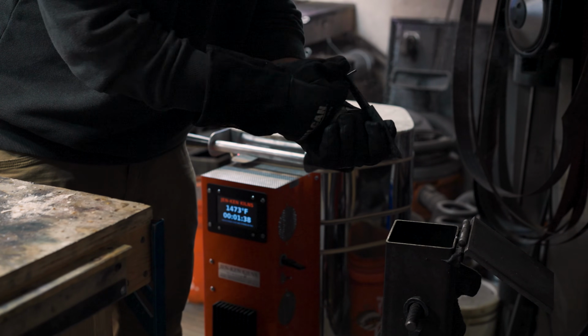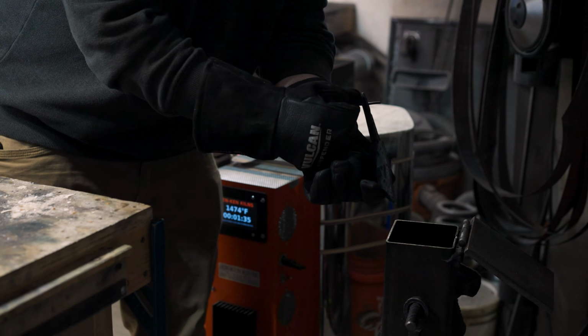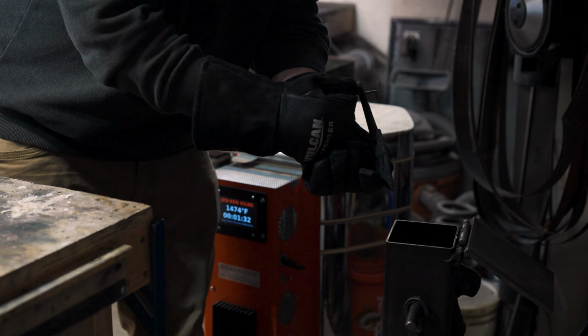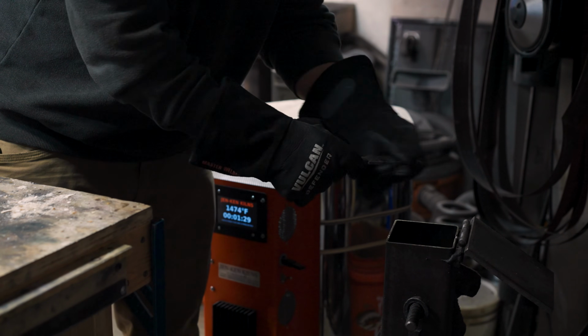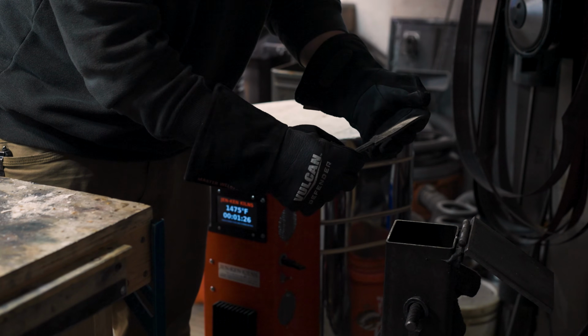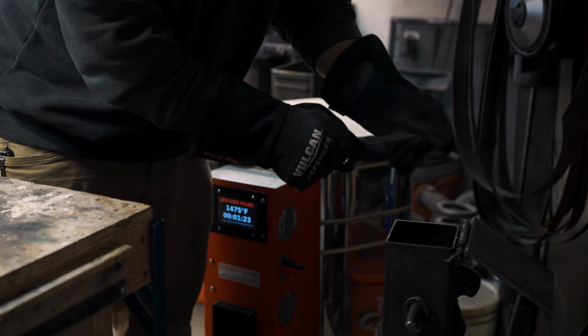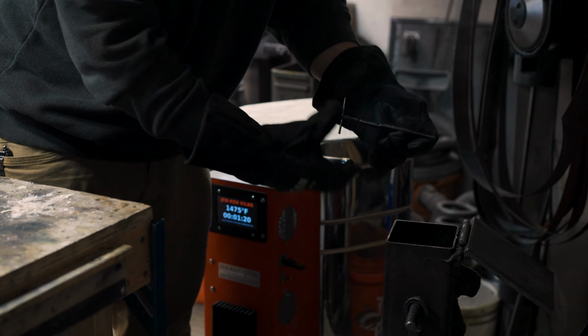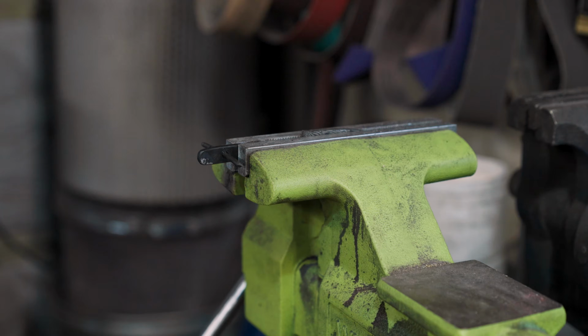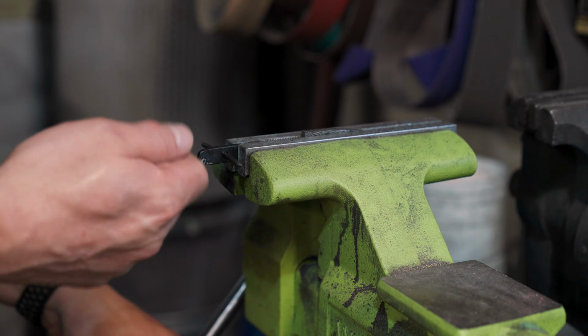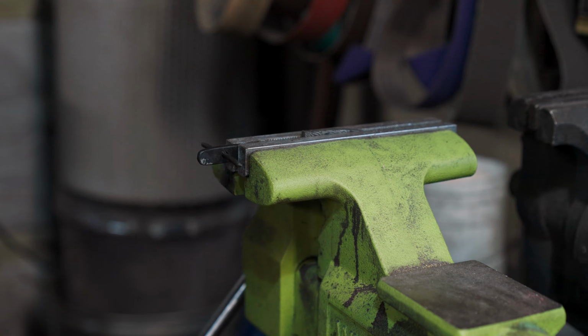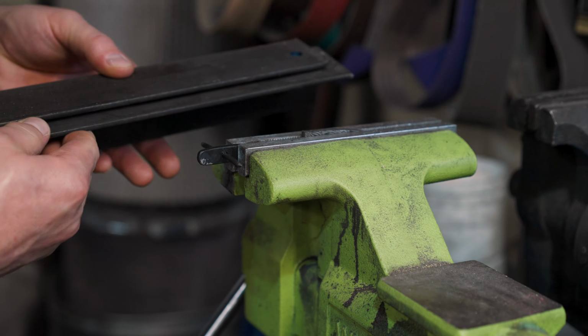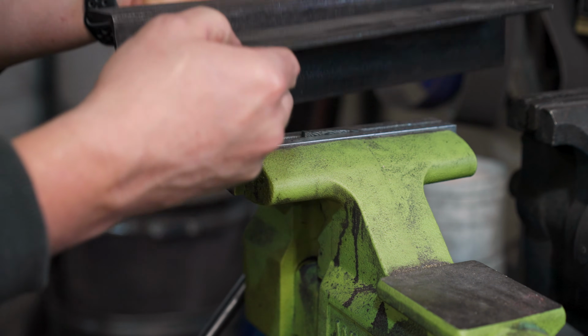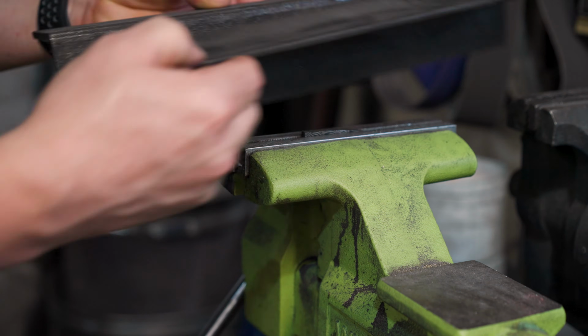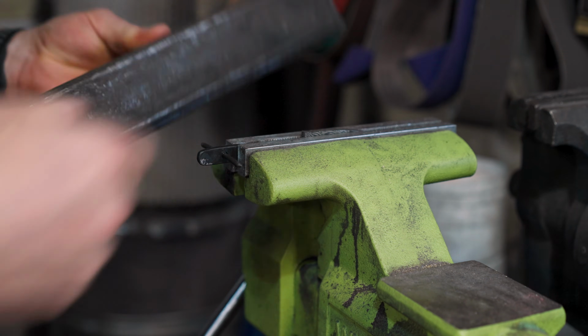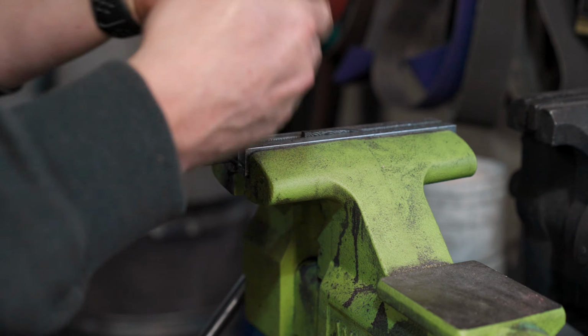And then I will check for warping. So kind of look at this straight on, and we're pretty good. The tang's kind of shifting to one side a little bit, but we're okay. So I'm gonna take this and lock it down in the vise, and that way it'll cool a little quicker and help keep it straight as it's cooling. So here you can see I just basically locked it down in here. If I had a longer blade, I'll take these pieces of angle iron and put them inside the vise to give me essentially a longer vise. But because this one's so short, it fits in the vise just fine.